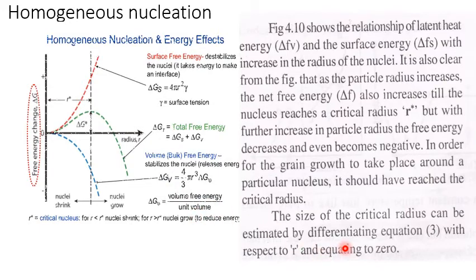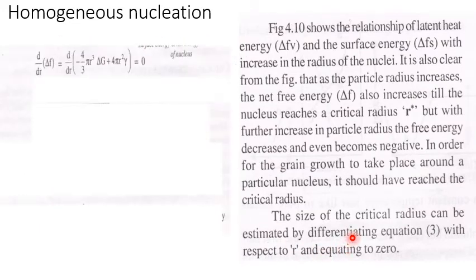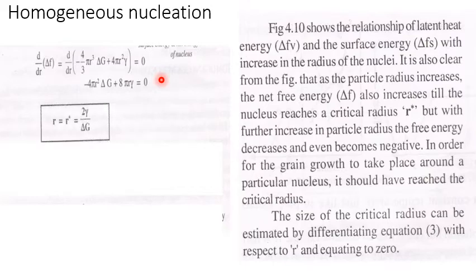So how exactly are we going to get that zero? We take the differentiation of the free energy and set it equal to zero: d by dr of [minus 4 by 3 pi r cube delta G plus 4 pi r square gamma] should be equal to 0. By differentiating this with respect to r and equating to zero, we get the critical radius r star equal to 2 gamma divided by delta G.